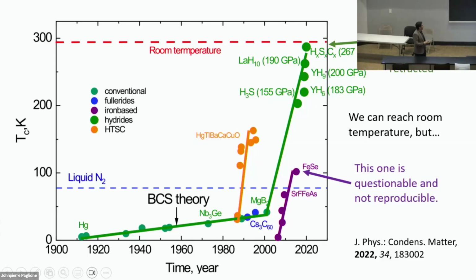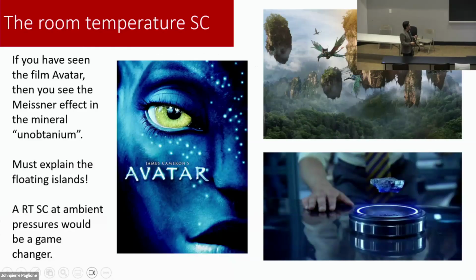And then for this one, for example, iron selenide at 100K it's not really been reproduced with resistivity measurements on a single crystal or any other kind of bulk material. So be careful when you see sometimes this, the literature and looking at these plots. But I think it's still exciting to think about, for example, hydrogen and hydrides, whether those can be superconducting. And I still think it's interesting to look at the iron selenide materials and see if there are other ways to boost that TC. So I'll leave it at that.